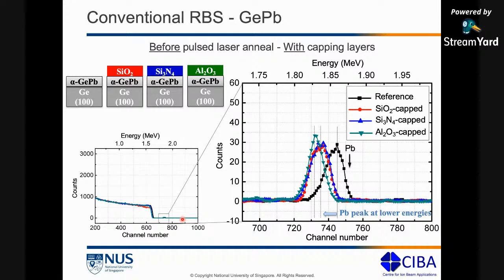So typical dopant levels for converting a semiconductor to a direct bandgap semiconductor are fairly low. They are on the order of 3% or even lower. So the lead is not going to be very significant when you see it in RBS. So we had to zoom in, but once we zoom in, this is what we see. We have the lead from the reference sample coming out at a higher energy. Why? Because it's on the surface. And then we have the lead from the cap samples, which come out at lower energies because of the capping layers on the top. Right. So this was our starting point.